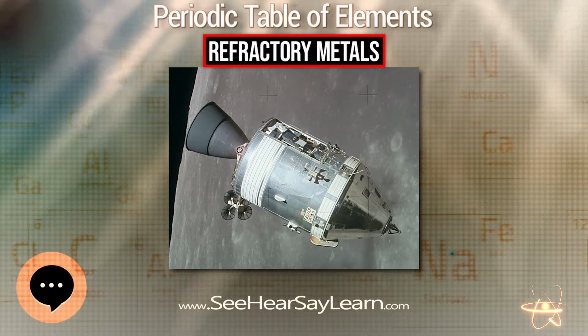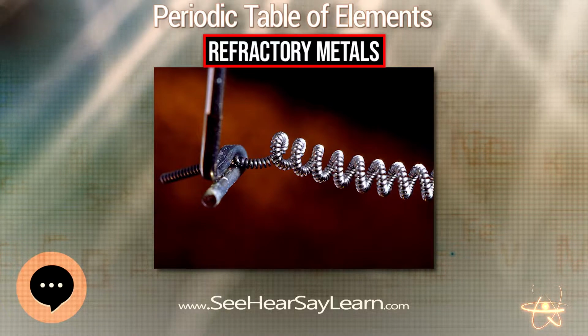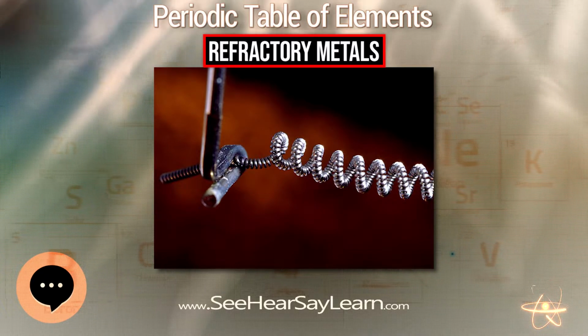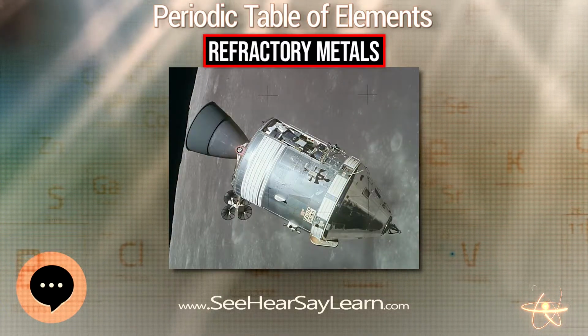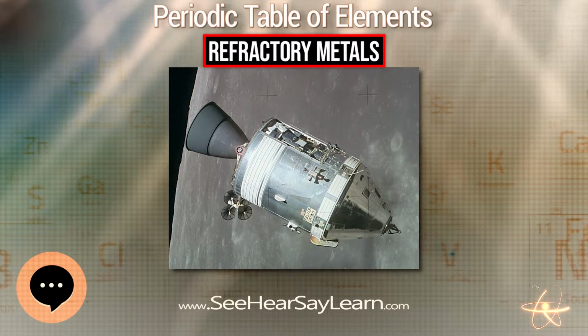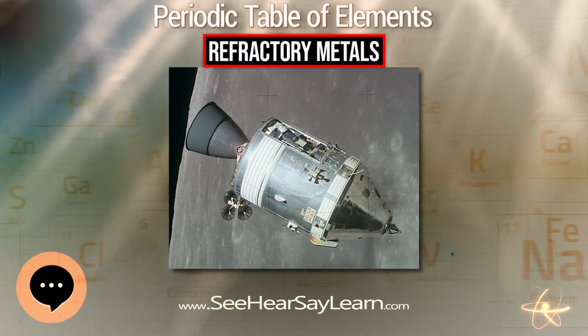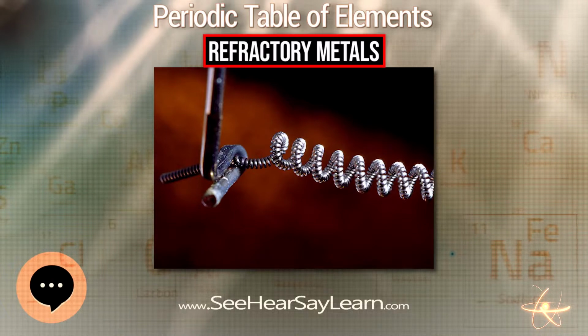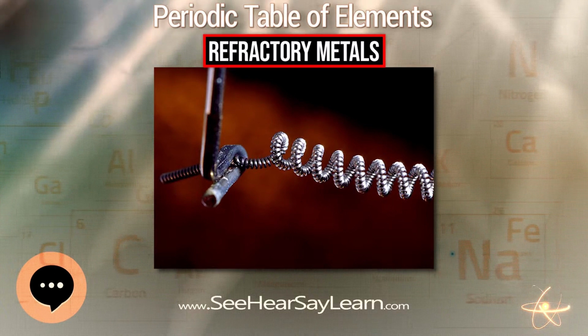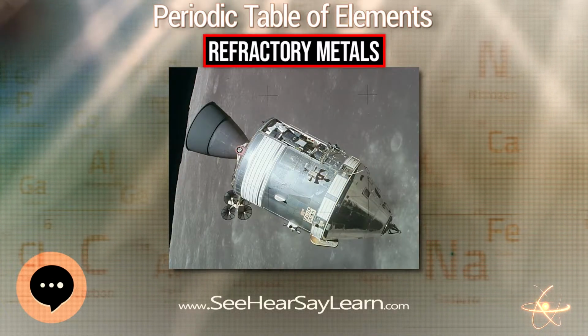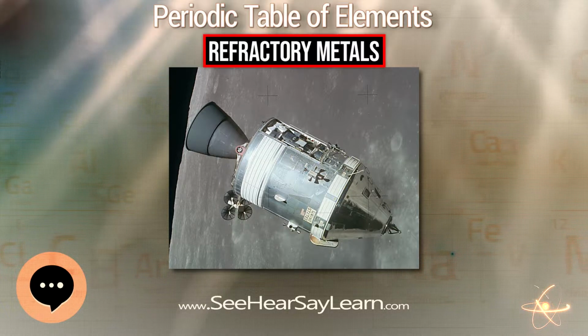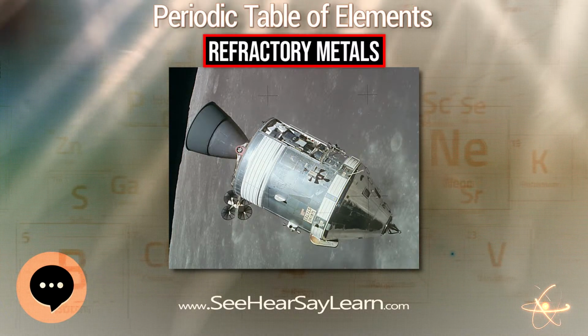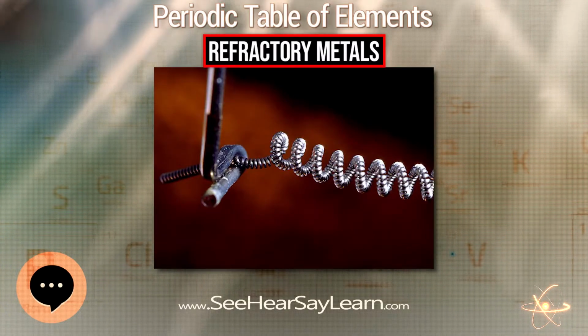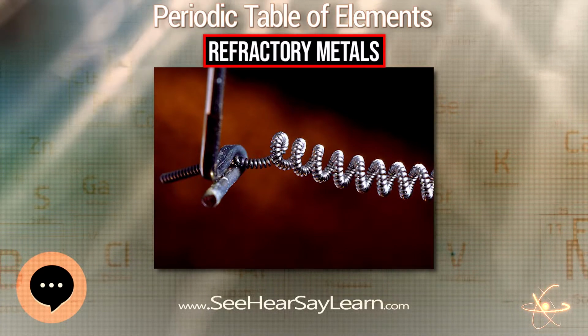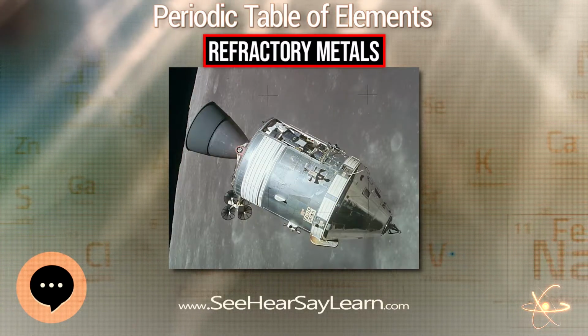The high resistivity of MO30W, an alloy of 70% molybdenum and 30% tungsten, against the attack of molten zinc makes it the ideal material for casting zinc. It is also used to construct valves for molten zinc. Molybdenum is used in mercury-wetted reed relays, because molybdenum does not form amalgams and is therefore resistant to corrosion by liquid mercury. Molybdenum is the most commonly used of the refractory metals.